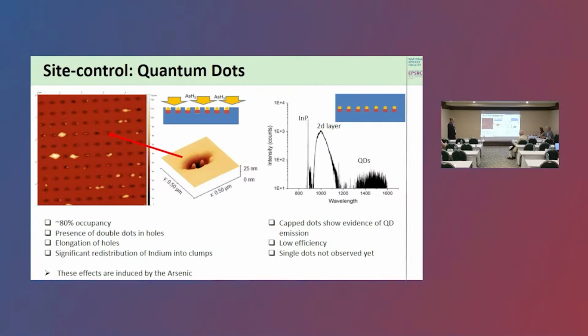So this is good news because it means that the process works. We can site control the indium drops, we can take the advantages that we've discussed about lack of strain, etc., and we can play around with the interaction between the droplet and the hole and etching, but we can maintain the site control when we convert into dots. This is only AFM images, so what we need to do is show that we get good quality dots.